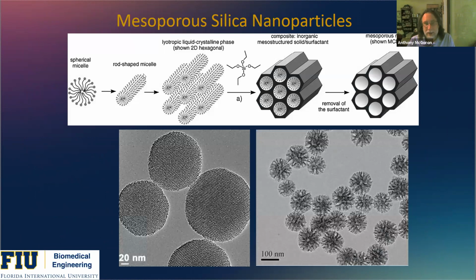So mesoporous silica particles, which I'm very interested in, although I've also investigated other types of particles that I'll briefly talk about, start with a surfactant, and the surfactant creates a micelle, and these micelles under optimal conditions can produce rods or other arrangements. Add a silica precursor to it, and silica polymerizes and condenses around the micelles, and then when the surfactant is removed, it results in some very ordered porosity in these nanoparticles, and the drugs can be delivered in these pores.